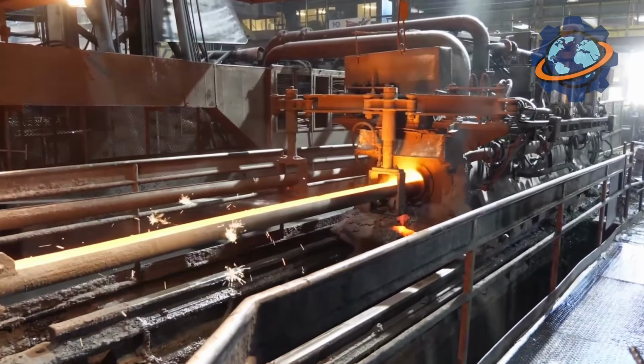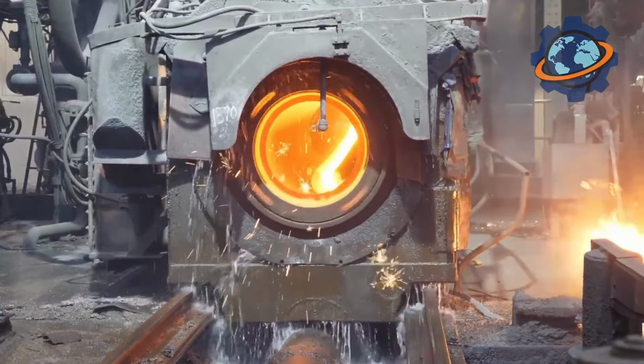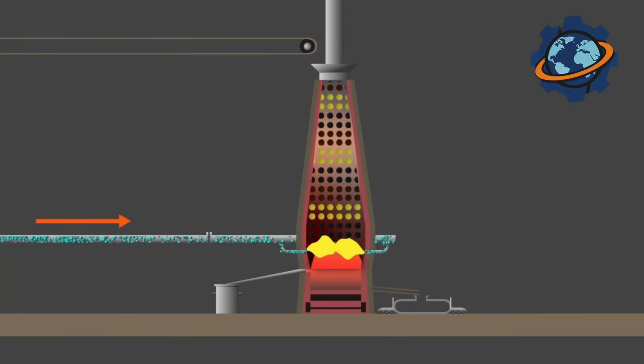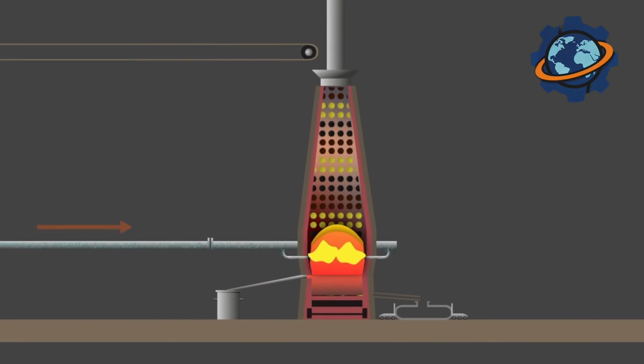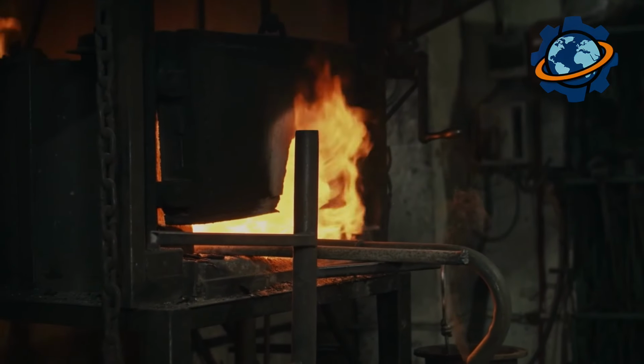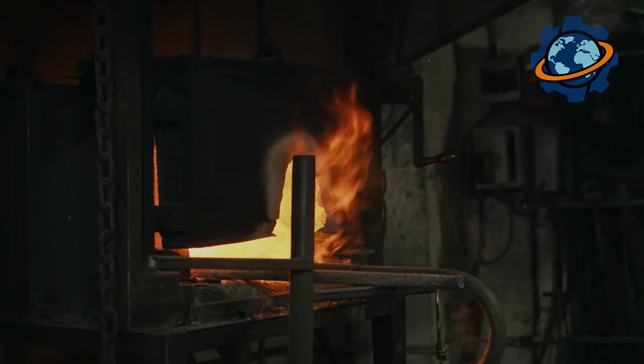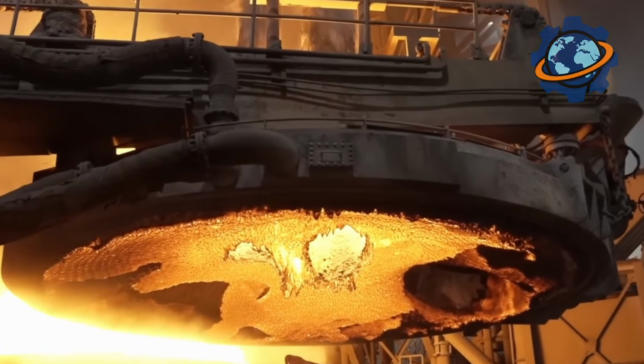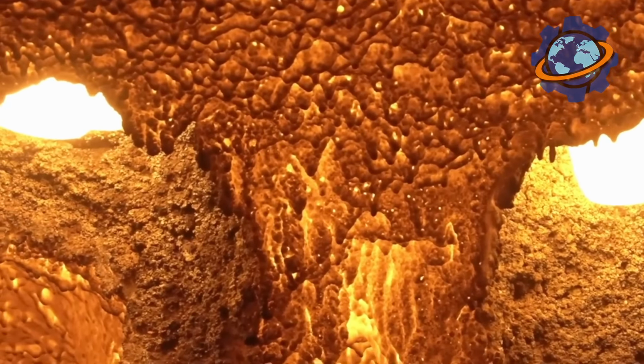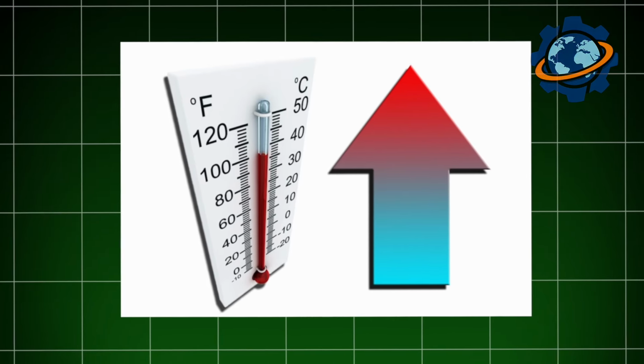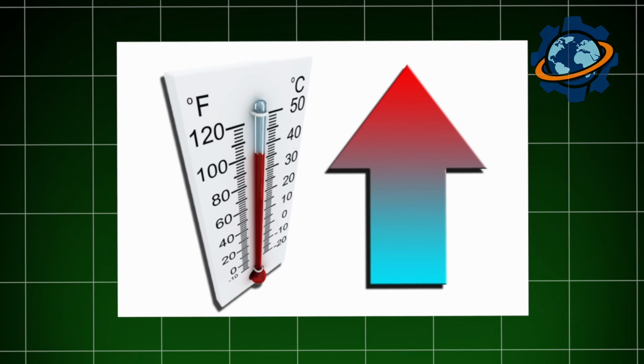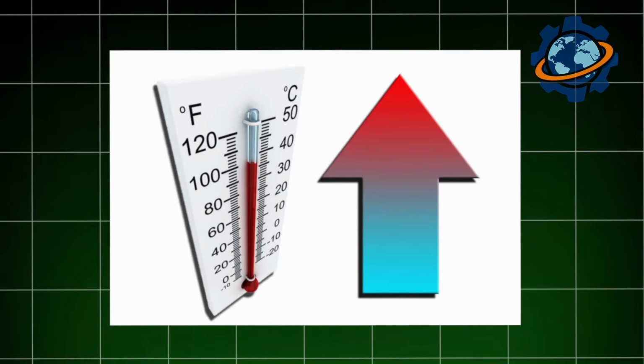The roasted concentrate, zinc oxide, is cooled and mixed with coke, crushed coal. The proportion, 3 parts oxide to 1 part coke. This mixture is loaded into vertical retort furnaces, steel towers 50 feet tall, lined inside with refractory silicon carbide. Heating begins. Temperature starts climbing. 1,800 degrees, 2,000 degrees, 2,200 degrees.